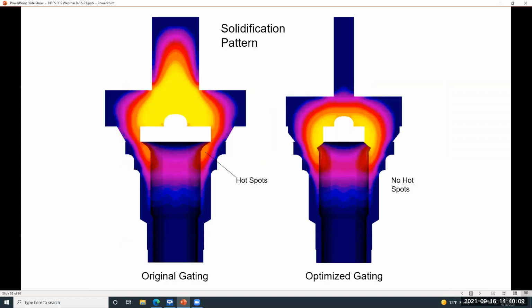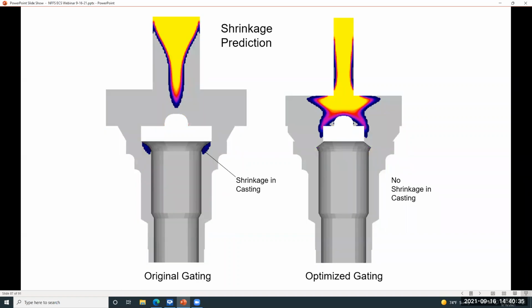Let's look at a comparison. These are slices through the two models showing the solidification pattern. This shows the initial area where we were getting shrinkage or a hot spot inside the casting. This shows the change where that was pulled up out of the casting and out into the feeding system. Here's our shrinkage predictions. Originally, we had shrinkage in the casting. And finally, there's no shrinkage in the casting, and our yield is 15% greater at the same time. So we've been able to get a great improvement while improving casting quality at the same time.